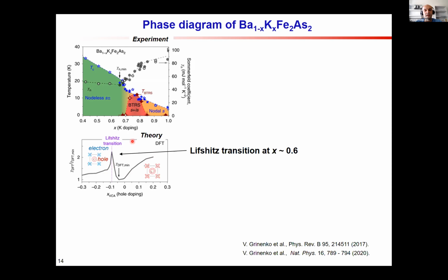However, all other parts, I would say, look quite similar, which allows us to roughly relate this change in Sommerfeld coefficient and critical temperature to the Lifshitz transition, which happens around 60%. In addition, Ilya provided us calculations of the critical temperature using a 4-band model. And one can see that the critical temperature also behaves similarly to the experimental one: it decreases and then changes faster above the Lifshitz transition, and it has this BTRS state roughly where this critical temperature flattens, on the right side of the Lifshitz transition.